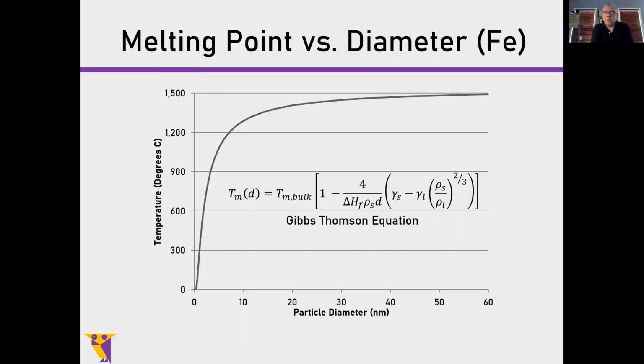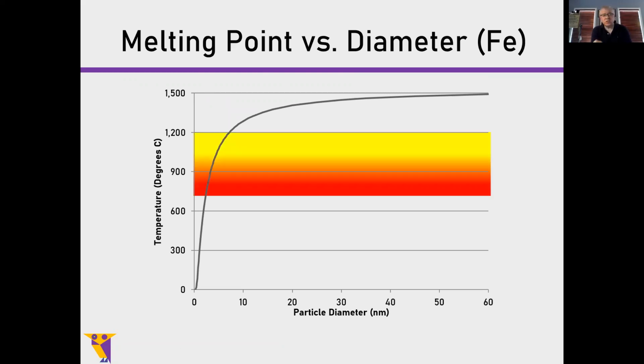Now, here's something that's really interesting also as you drop down to these nanoscales: the melting point changes. This isn't me, this is Gibbs and Thomson 150 years ago studying this with the Gibbs-Thomson equation. And if you look at it, it looks extremely straightforward. Enthalpies of fusion, densities, sizes, surface tension, surface energies, all of them are in there. It's just arranged quite nicely. And you can see the size relationship between the particle diameter and the melting point. So at the reaction conditions where you typically are for these things, most of the particles in that range will remain liquid. And so you'll grow nanotubes easily because those particles will remain liquid.